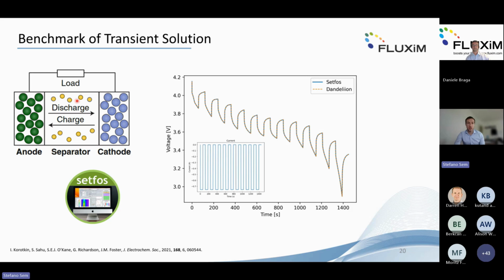But we didn't stop there, so we continually developed Setfos for batteries also after the end of the project. In this case, we made a simulation. This is a GITT, so it's current pulses. And we see here a comparison between Setfos and Dandelion, which is a well-established simulation software used for batteries. And we see that the results are pretty much identical for the entire curve.